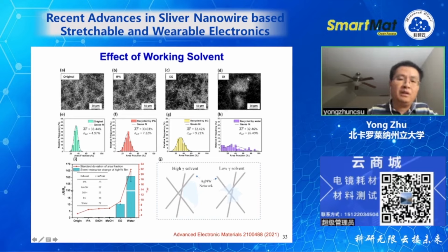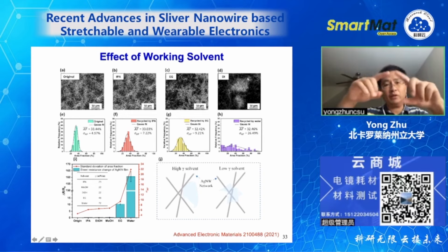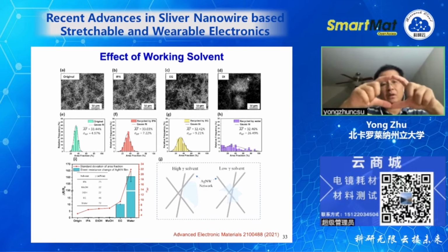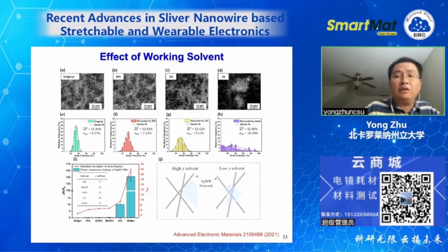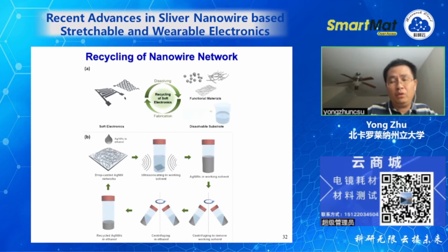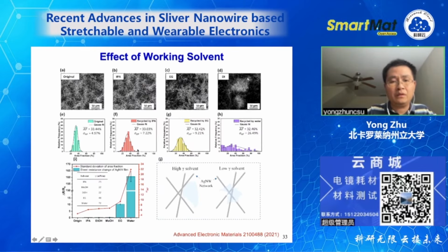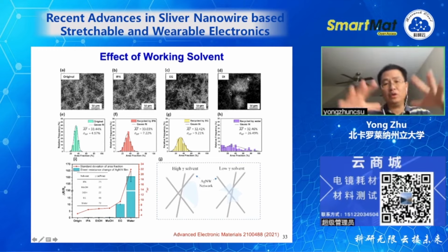So then we measure the nanowire distribution. We define something called the area function: for a given unit area, the number of silver nanowires. Then you can plot this, and from there you know the density and also the variation. The variation tells you if the distribution is uniform. If it's uniform, it's going to be a very narrow distribution. But if it's not uniform, you're going to have a wider spread in terms of the standard deviation.